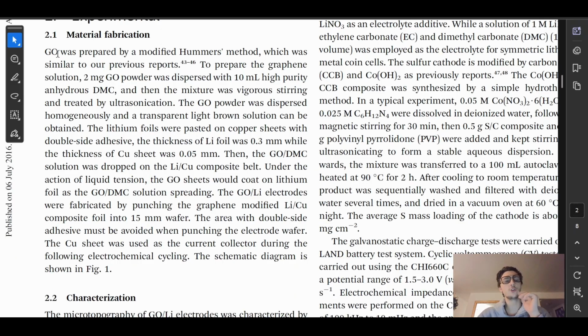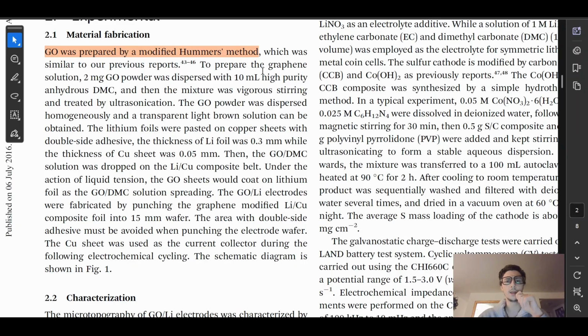Material fabrication. GO, which is graphene oxide, was prepared by a modified Hummers method, which was similar to our previous reports, 43 to 46. So, modified Hummers method, interesting. I'm just going to highlight that, looks pretty cool. To prepare the graphene solution, 2 milligrams graphene oxide powder was dispersed with 10 milliliters high purity anhydrous DMC. They mentioned DMC before, I have no idea what it is, but I'm assuming it's some kind of liquid. We'll see. And then the mixture was vigorously stirred and treated by ultrasonication. Maybe there's some English grammatical stuff going on here. Cool. The graphene oxide was dispersed homogeneously and a transparent light brown solution can be obtained.